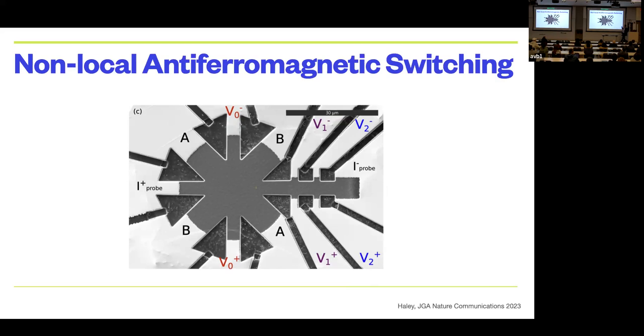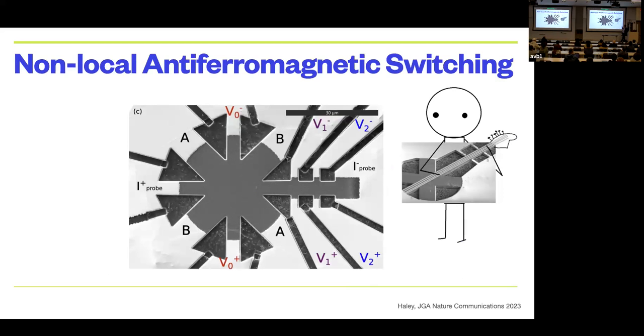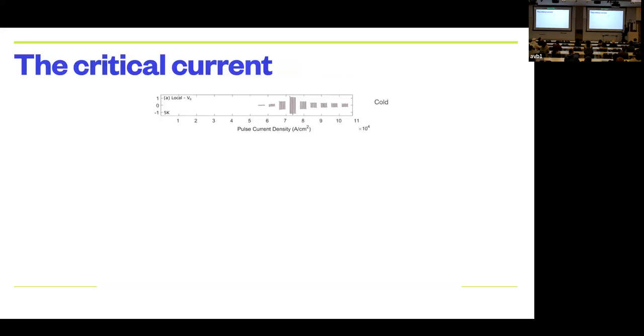Here's one thing that we also did. We made a device that looks a little bit like a guitar. And we pulse current in the AB direction, which changes the domain boundaries in this part of the sample. But actually, we could see that signal propagate all the way to 35 microns away from the active area. As far as I know, that's as far as anybody's been able to. It's basically a way of switching memory over in that corner over here by having an electrical pulse over here. So it's like non-local switching. So it was a very powerful, very efficient, very fast way of doing this.